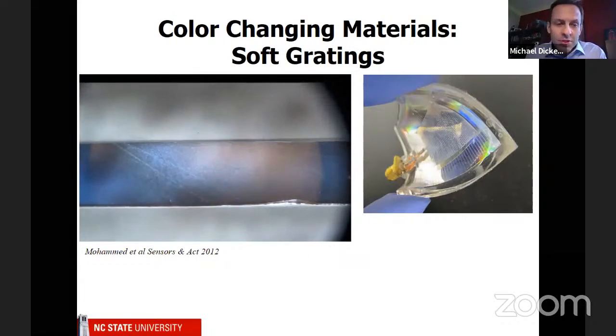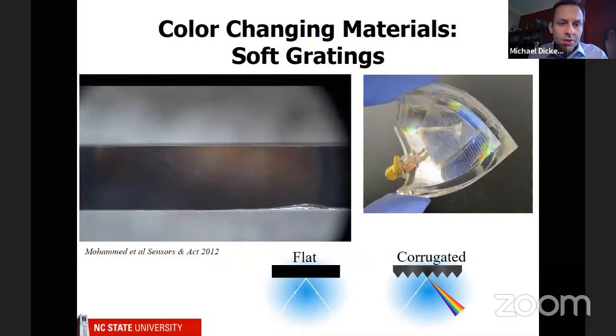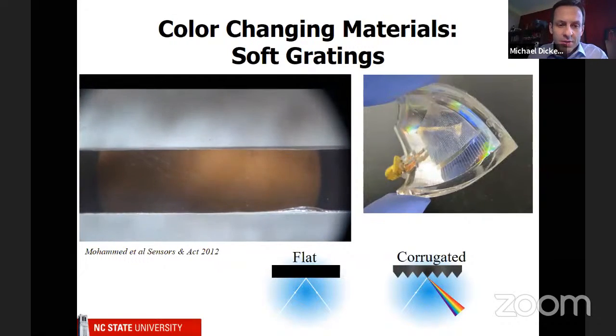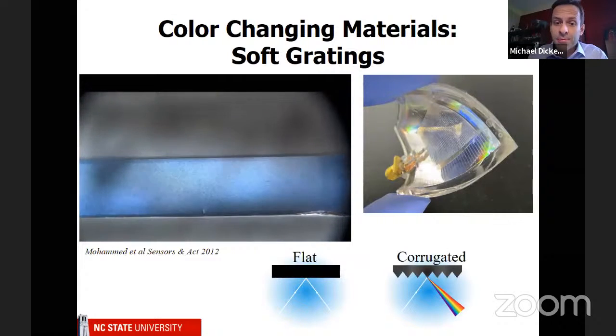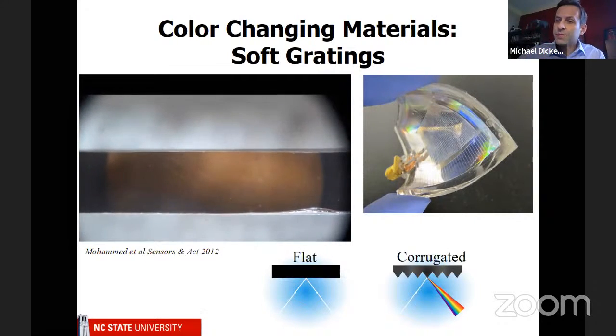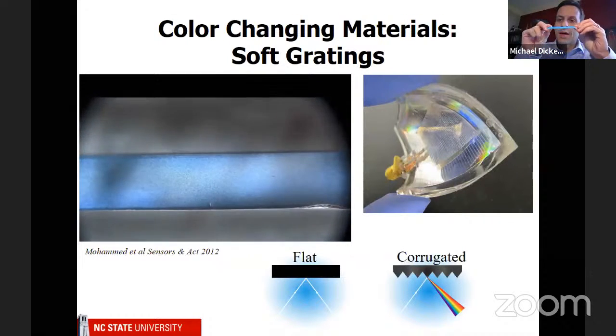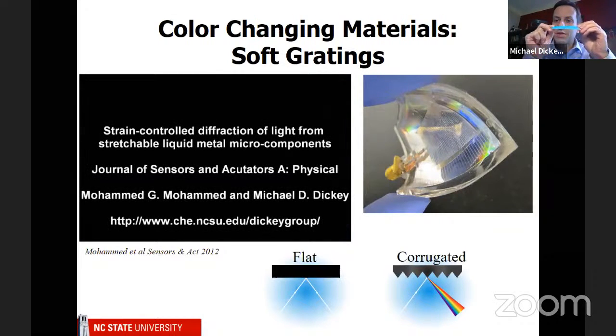But it turns out that what's happening here is actually quite simple. If you have a flat surface and light comes down and hits that surface, it bounces off like a mirror. However, when you squeeze something rigid, like that oxide layer, it's going to form little buckles, just like what's happening here in my hand. When you squeeze these things, you form little corrugations. And those corrugations act like diffraction gratings that cause the light to diffract, and therefore it appears colorful. So this is kind of cool because we're able to get color from structure, from shape, not from a dye.